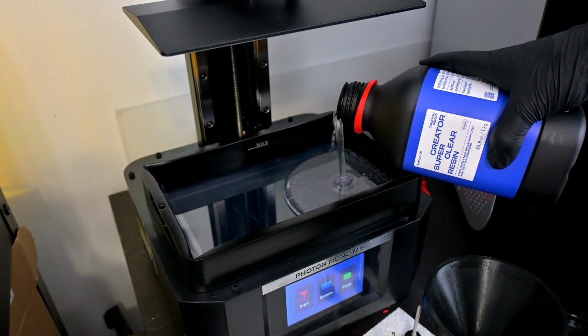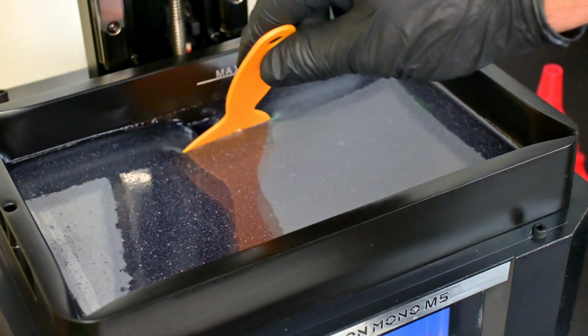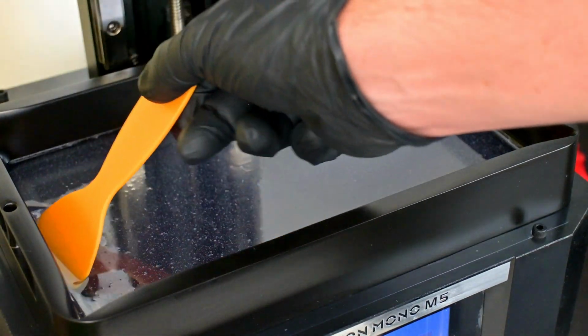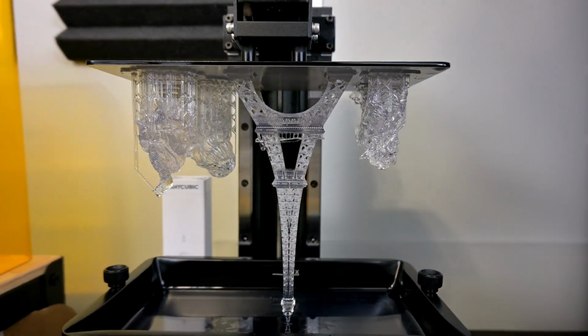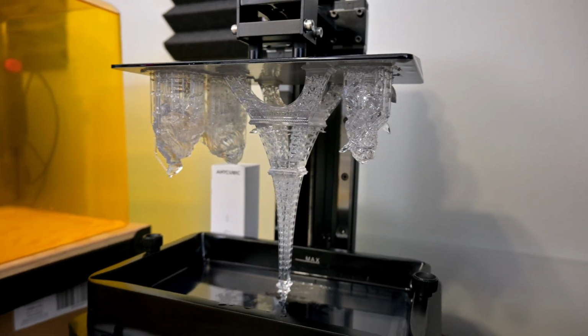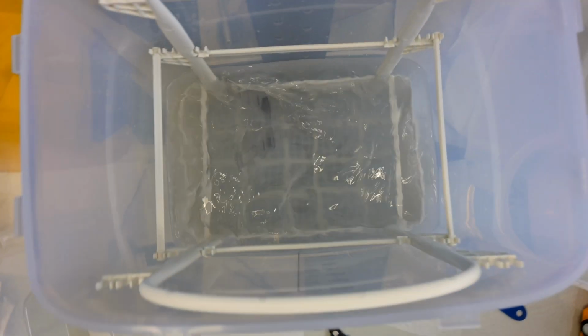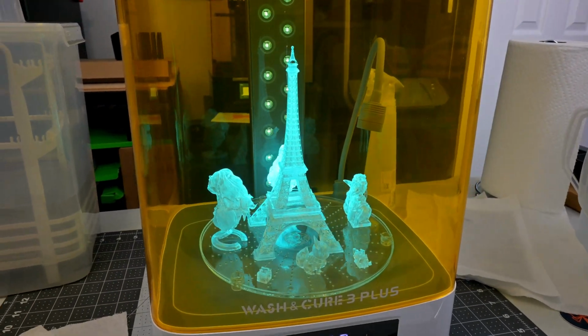So let's swap over to the Creator Super Clear. The print settings are very similar, with equally long exposure times. With it being a clear resin, we can watch the exposure in action. Recommended lifting speeds were a bit faster than the Creator Tough resin. Once finished, the Creator Super Clear has a recommended wash time of 10 minutes, followed by a post-cure under UV lights of only 5 minutes. I love watching the Super Clear prints cure though, it looks really awesome.